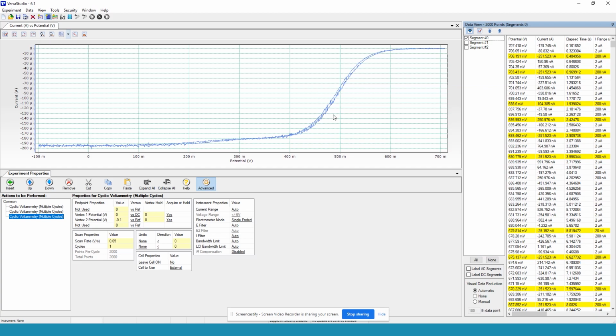Now, after this, in this middle area, we see that the graph becomes a bit more linear. This is because we, on the one hand, have the kinetics contribution, but on the other hand, we also have the diffusion limitations. So because of this, the graph starts to lose its exponential increase and becomes a bit more linear. In the final area, we see that the current will actually start to level off. And this is purely because of diffusion limitations. So these are the 3 regimes that we see in this area. So we have the kinetics limited regime, we have the mixed regime, and we have the diffusion limited regime.